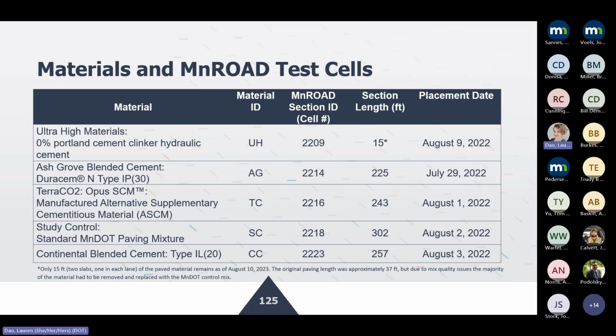The initial formulation that Ultra wanted to use was an alkali activated cement, but they could not dial down the mix design. So then they provided another formulation which did not have any Portland cement in it. And material number 2 there, Ash Grove Blended Cement, that's a type 1P30 cement. It's a blended cement. And then the third material there is a TerraCO2 Opus SCM. This is a manufactured fly ash, or as they call it, a manufactured alternative supplementary cementitious material. The mix was a type 1P10 with 35% replacement for cement for this particular manufactured fly ash.